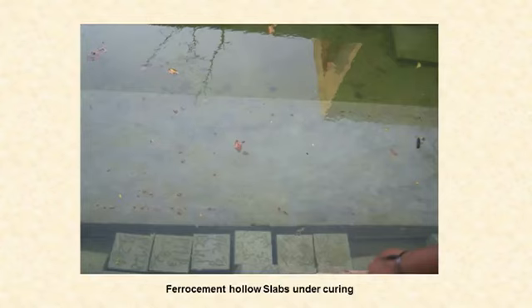And after a day, the mold was removed, and the slabs were cured under complete immersion condition in tanks. The slabs were cured for a period of over 28 days, and after that, they were taken for testing.